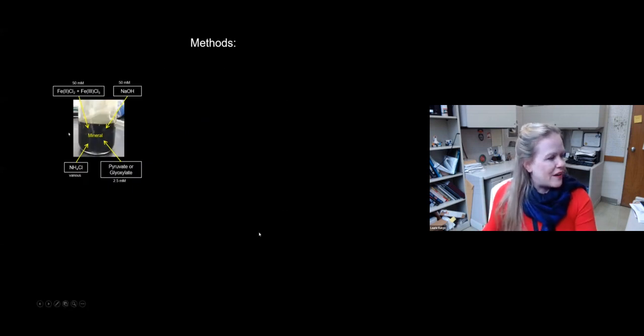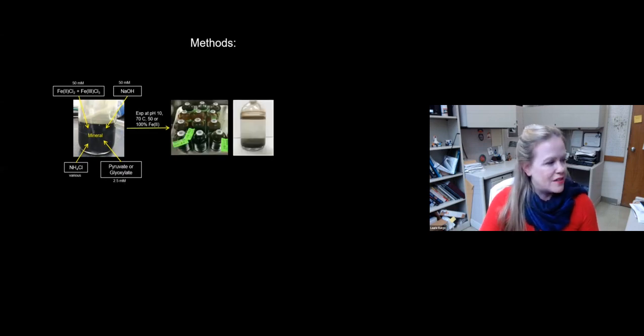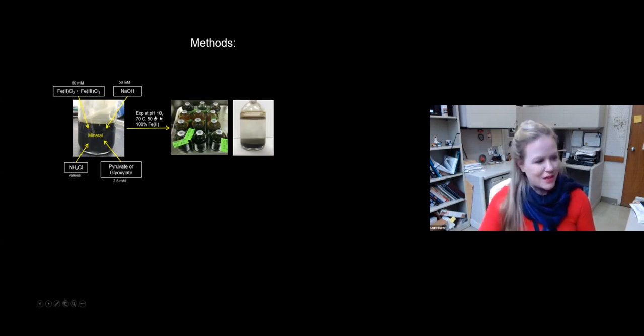So here's the methods for these experiments. Again, we take the vial, we add the iron salts at whatever ratio we're testing. We add sodium hydroxide to precipitate the mineral, and then we titrate to pH either 10 or 7, depending. And then we add ammonium chloride at various concentrations, and then we add our organic at 2.5 millimolar, and we add either one or the other, but the reaction is the same as if they are mixed. So we react this at 70 degrees Celsius, maybe 50 or 100% Fe2, depending, though we have a range of iron redox states. This says pH 10, but we've also done pH 7.